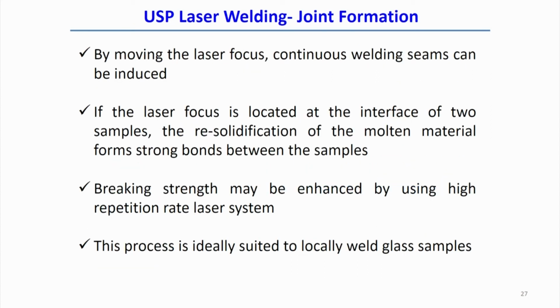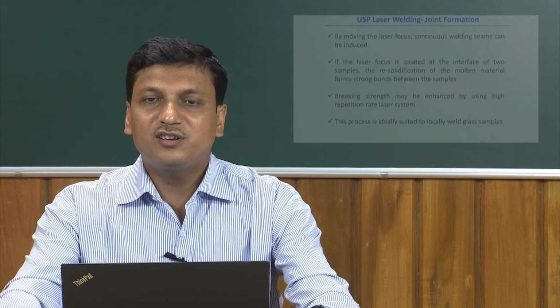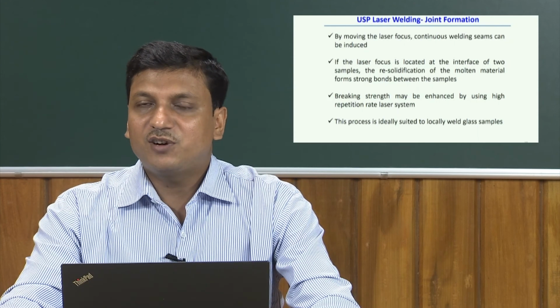Joint formation is similar to conventional processes. Simply by moving the laser, a continuous welding seam can be induced, but if the laser focus is at the interface of the sample, resolidification of the molten material occurs, and that actually creates a strong bond. In such cases, definitely the mechanical properties can also be improved, or the mode of material joining can be decided by the repetition rate of the applied ultrashort pulse laser.